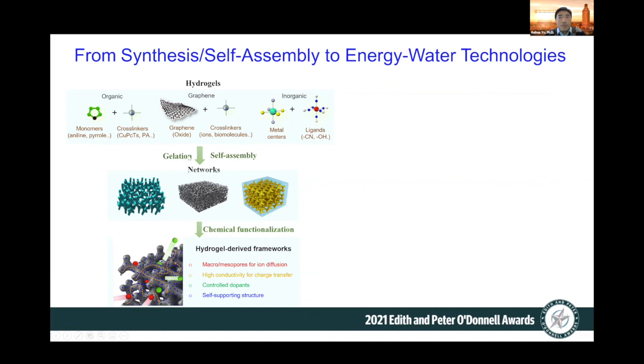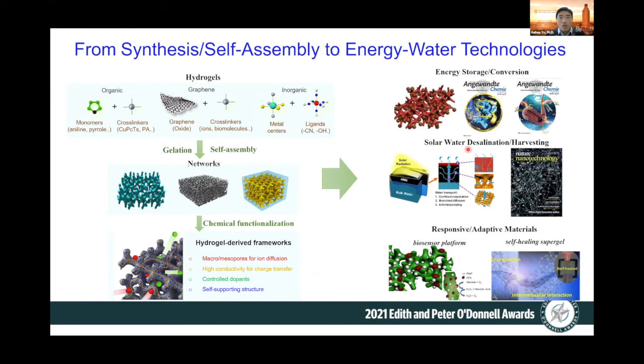In addition to the synthetic tunability, the micro- and nanostructure of hydrogels can be explored as both precursors and templates for architecting 3D frameworks of electrochemically active materials. These very unique 3D interconnected porous structures of hydrogels and hydrogel-derived materials enable fast charge and mass transport while offering large surface areas. They can also be regulated in terms of polymer-water interactions to achieve desirable water retention, absorption, and evaporation for water-related applications. We have been exploring various applications in energy storage and conversion, solar water desalination and harvesting, and responsive adaptive materials. I will start with two examples on how we can synthetically tune this class of materials.